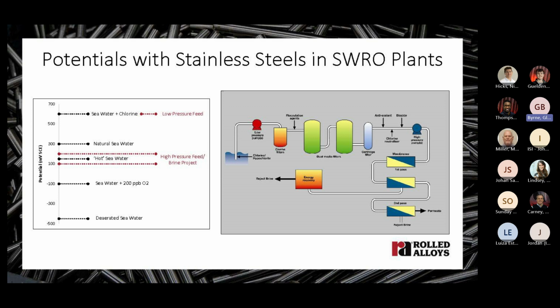And this actually prevails from the seawater intake, because chlorine is usually added through the intake pump, up until we get to this point where the chlorine is neutralized. So this condition prevails at 20,000 ppm chloride at 600 millivolts of potential up to this point in the system. The chlorinated feed then has to be dechlorinated before it reaches the membranes, as the membranes are normally chlorine intolerant and would be oxidized. This gives a high salt passage into the permeate that you don't want.